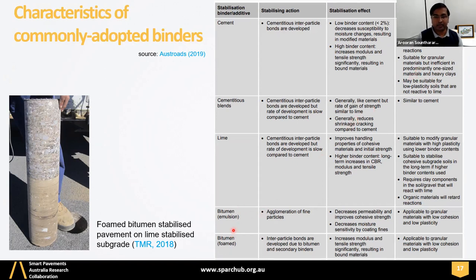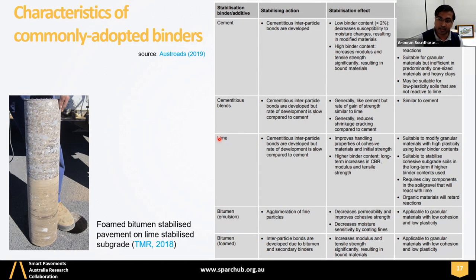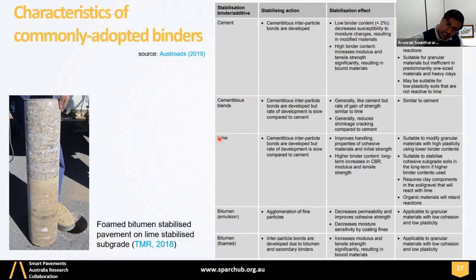And bitumen and foam bitumen, we'll cover later. And lime, which is commonly used for subgrade stabilization in Australia. The subgrade here means soft subgrade. If the subgrade has reasonable strength in terms of CBR, California bearing ratio, greater than five in Australia, it is considered reasonably good. CBR less than five is considered a poor subgrade, and normally they do some treatment like lime stabilization and, in some instances, geogrid.